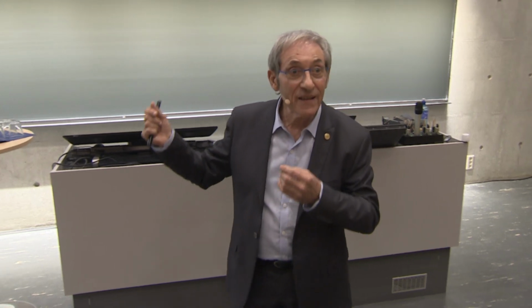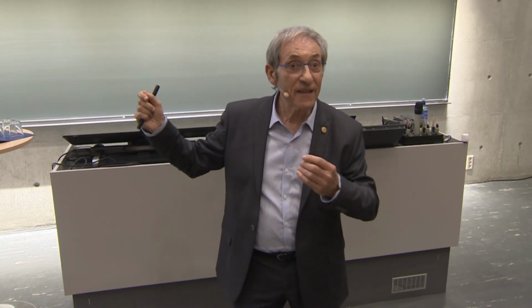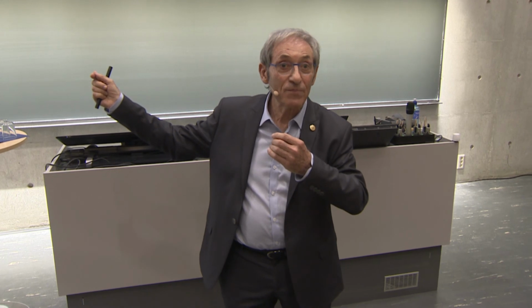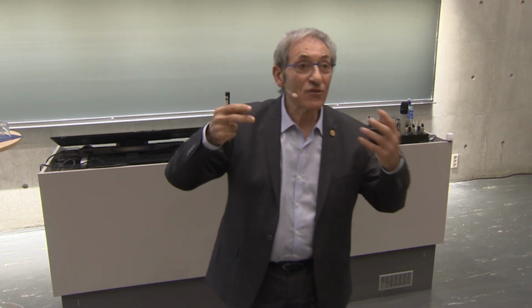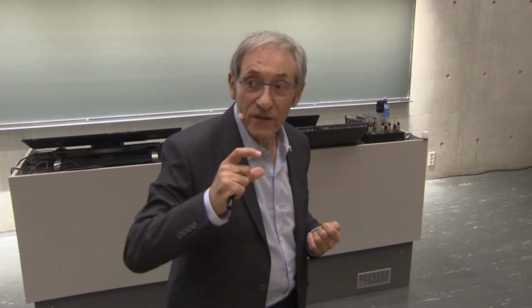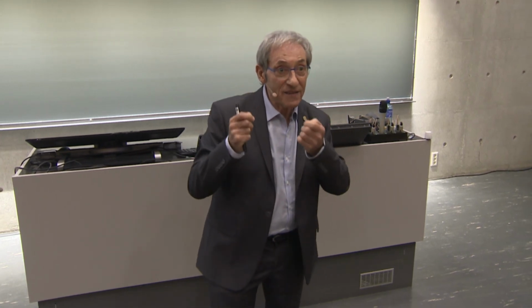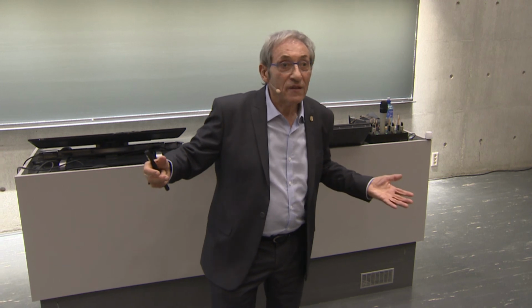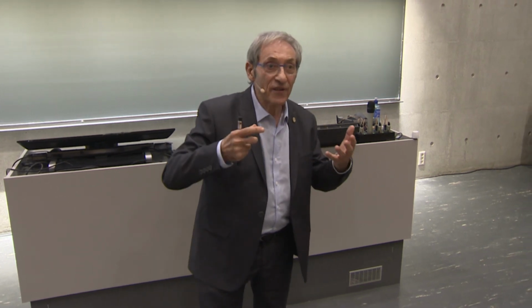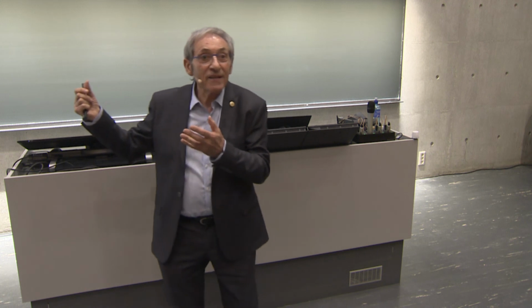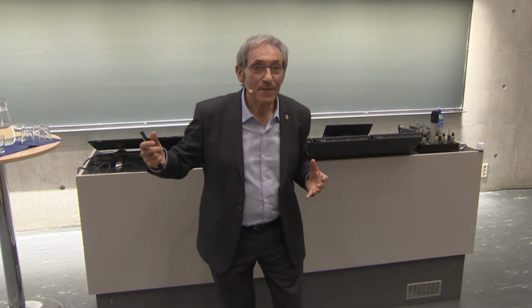So it's certainly an interfacial effect. That's why I'm talking about those papers that predict unusual conduction at interfaces, either by the exciton or by pairing of electrons and holes across the interface. It's not that the silver itself can do it. It's only the structure itself, and this is a nanostructure, and the interface is important. So this is where the entire story is about monolayers. It's not that we make a material, we make a structure at an interface. And this gives the unusual properties.